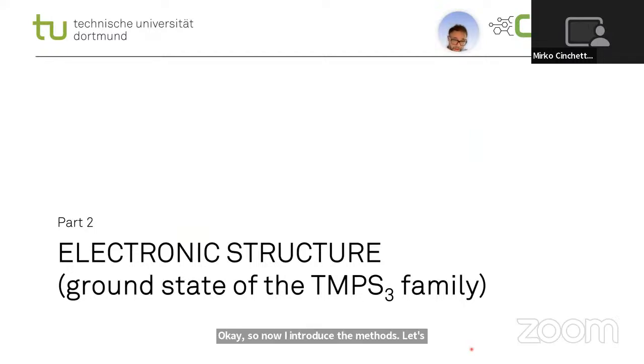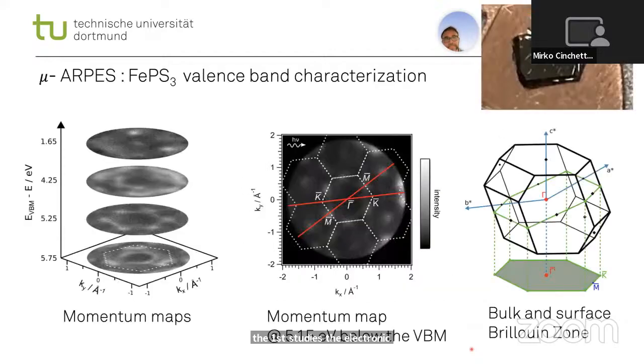Let's go back to the transition metal phosphorus trisulfide materials and first study the electronic ground state using ARPES. We performed the experiments on freshly cleaved crystals in UHV at room temperature. And what you see here are the momentum maps that I introduced before, recorded at different energies of the electrons. The energy is always referenced to the valence band maximum. What you can see in these images is that we have a hexagonal symmetry of these momentum maps, and this is good because the surface projected Brillouin zone, which is what we see in our experiment, also has a hexagonal shape.